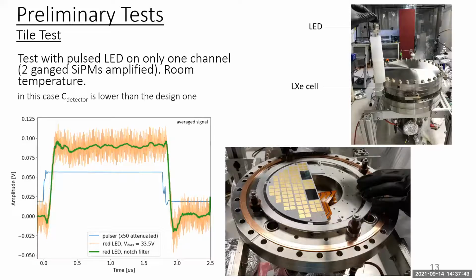This is a preliminary test that we assembled. We closed up the cell at room temperature, not cold yet, and we just pulsed an LED. You can see from this plot that although we suffer some high frequency oscillation, we are sensitive to the light, so the devices are active.